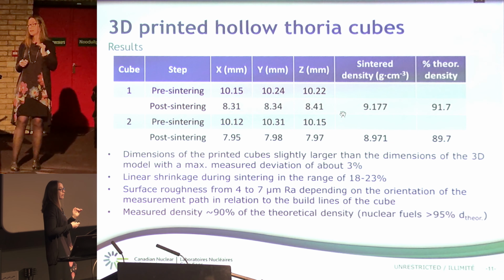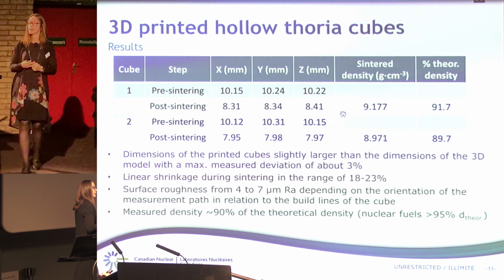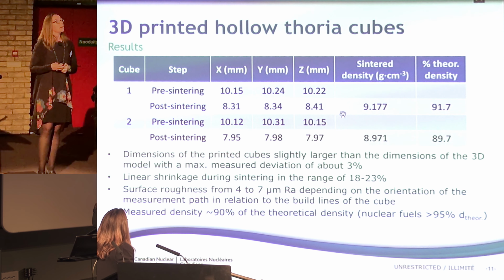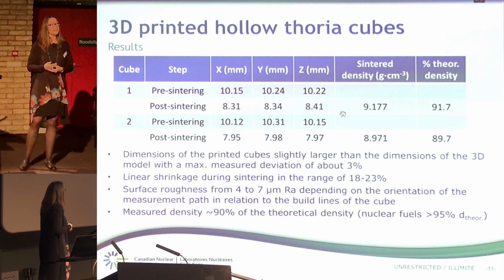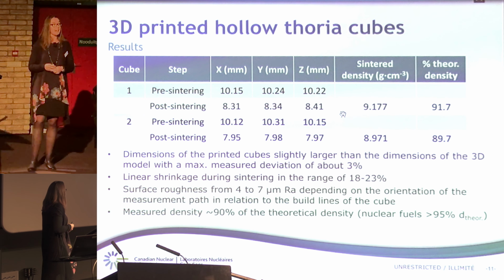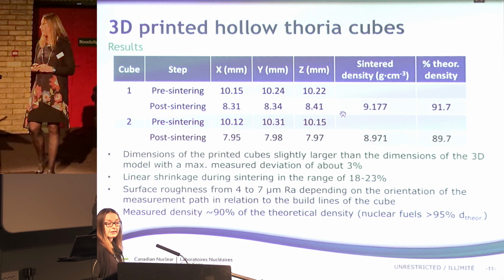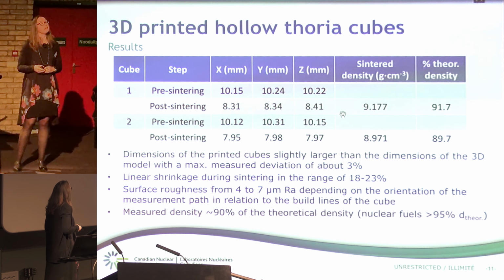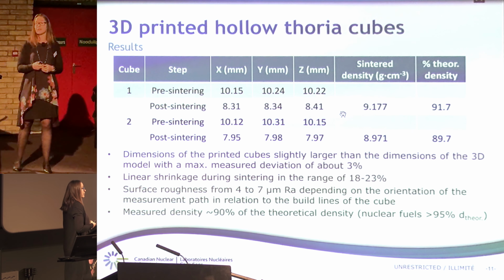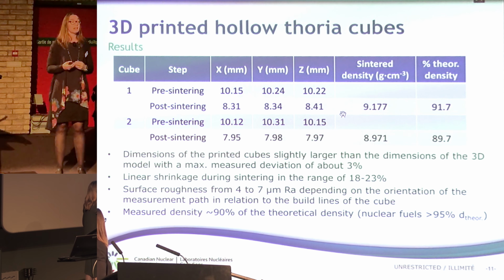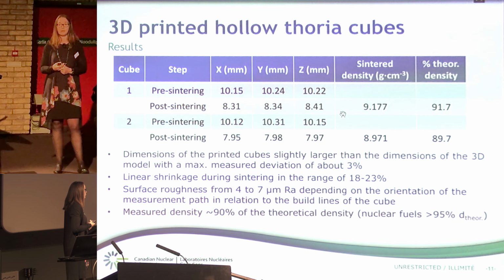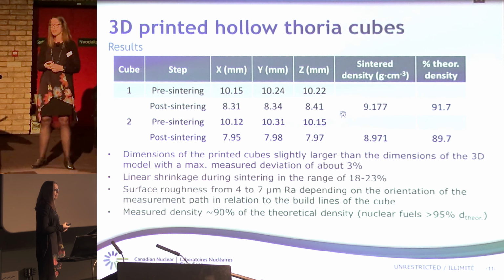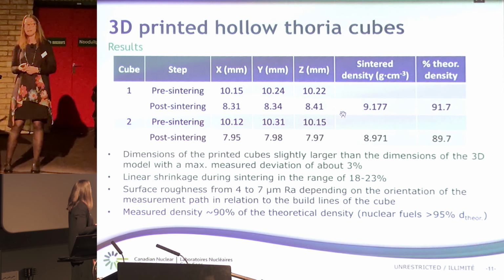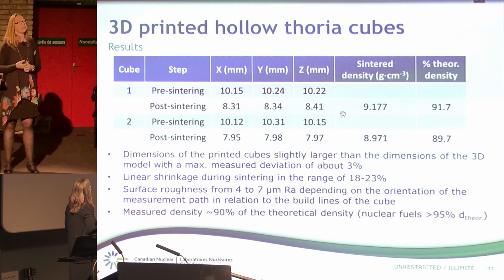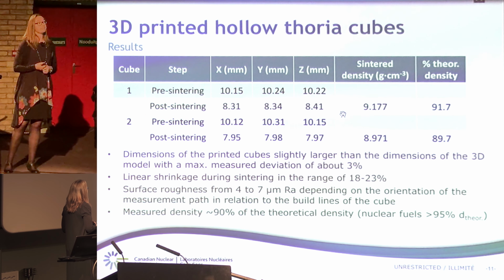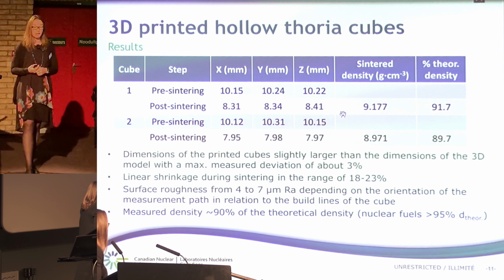Obviously, when we add layer upon layer, there is some anisotropy in the process too. We were pleased to observe, after our first trials, that the final parts were quite dense, with a value of about 90% of the theoretical density, which is still a bit low compared to the requirement for any nuclear fuel, which is over 95% of the theoretical density. But we are currently working on improving the density, and this density was measured by immersion.